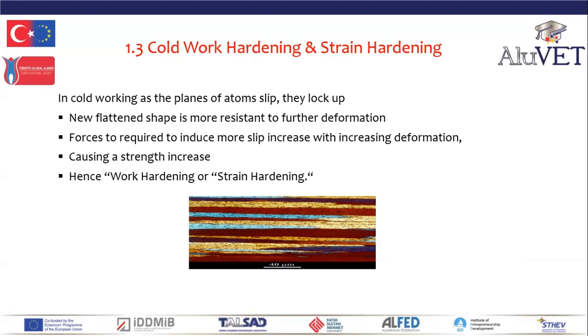As the severity of the deformation increases because of the lockup of the planes of atoms, effectively the new flattened shape becomes more and more resistant to further deformation. The forces required to induce more slip, more shape change, increase with increase in deformation. So the more we deform a metal, the more the force required to deform the metal further increases. Thus, cold work and the resultant slip cause a strength increase.